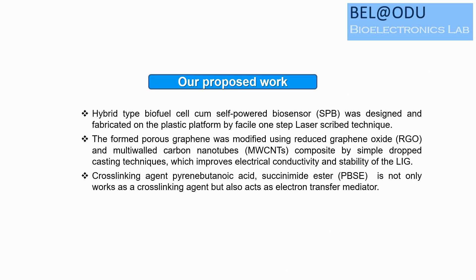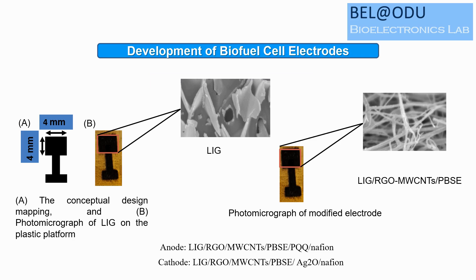Our proposed work: a high-performance self-powered biofuel cell biosensor (SPB) was designed and fabricated on a plastic platform using a facile one-step laser scribing technique. This technique forms porous graphene on polyimide tape by laser burning. The formed porous graphene was modified using reduced graphene oxide (rGO) and multi-walled carbon nanotube (MWCNT) composite by simple drop casting, which improved electrical conductivity. A cross-linking agent, pyrenebutanoic acid, succinimide ester (PBSE), acts as both a cross-linker and electron transfer mediator.